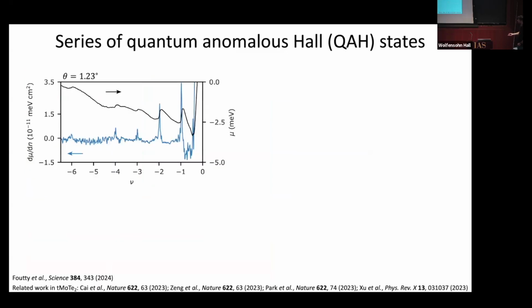And again, when we measure electronic compressibility at a particular spot, here I'm showing you data at 1.23 degrees, you can see as a function of hole filling factor, number of holes per Moiré unit cell, there are peaks at integer fillings, 1, 2, 3, 4, and 6. These correspond to energy gaps that develop within the Moiré bands. You can also see the step in chemical potential from integrating this. And so we'd like to know, are these trivial or are these topological?